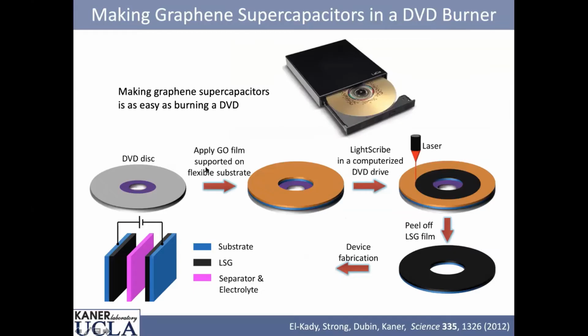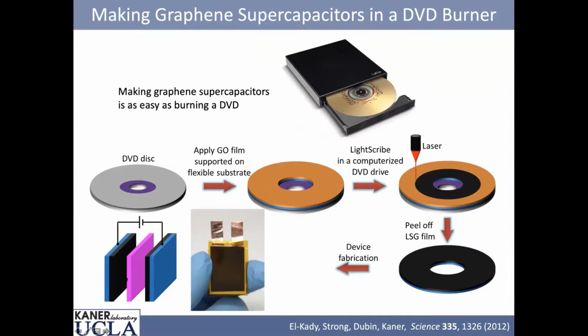So here's how we did this. We took our DVD, we put a piece of plastic, we coated it with graphene oxide. We hit it with a laser, but this time we tell the laser just darken the whole thing, turn it all to graphene. We peel it off, we cut it into pieces, and we build a cell that really looks like a battery, right? Two electrodes, an electrolyte, or a separator, we add a drop of electrolyte.